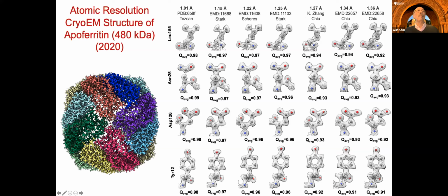So here are 4 amino acid examples I picked from all the structures. The column on the left is from the X-ray structure, which I consider to be the gold standard. You can see the resolvability of each of these heavy atoms, carbon, nitrogen, oxygen, is quite good across all these different microscopes and different settings. In addition to looking at the density, we actually quantify the resolvability. We have a numerical score that can rank the resolvability of different density maps and models. The important aspect is that we were able to create this almost identical density map in 3 different labs in 3 countries. That suggests that cryo-EM is definitely a reproducible technology at atomic resolutions.